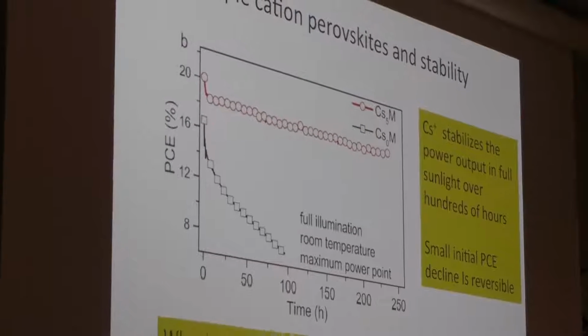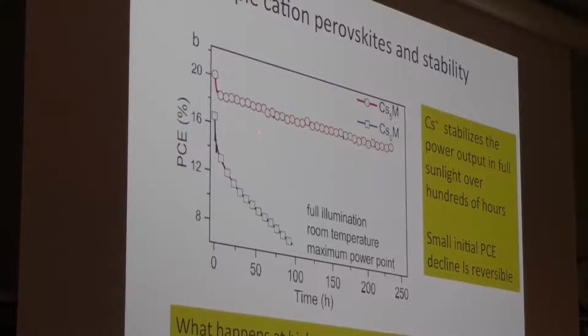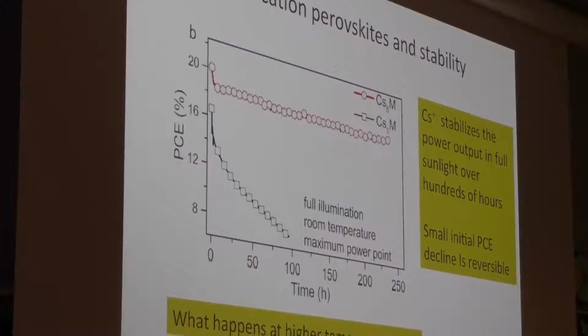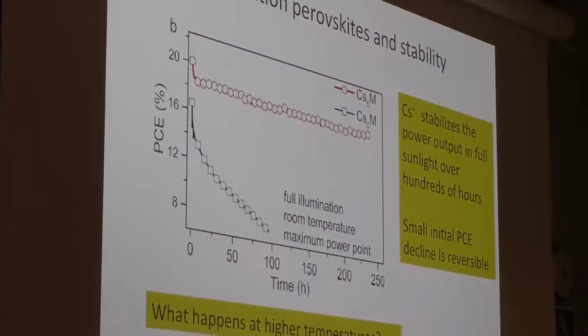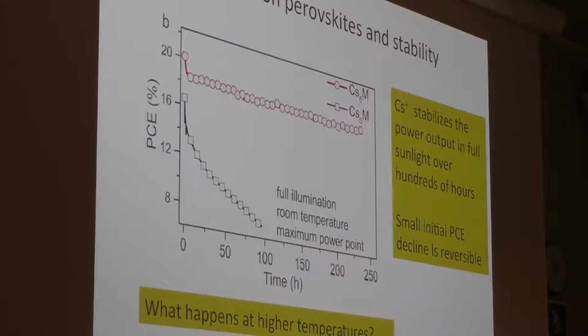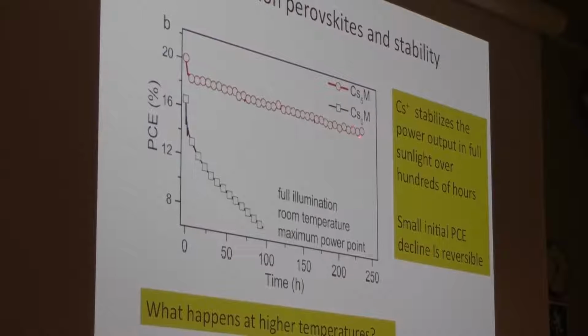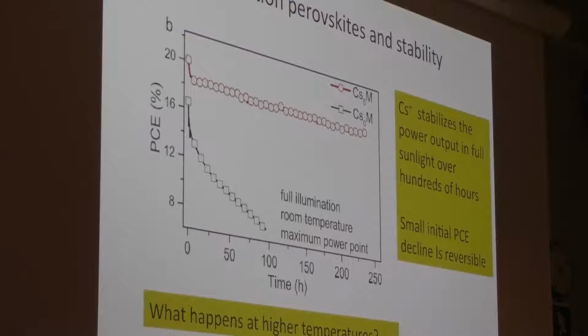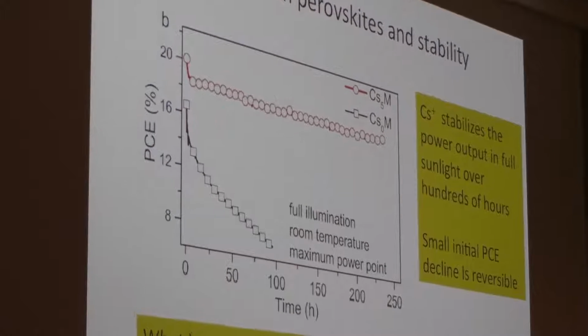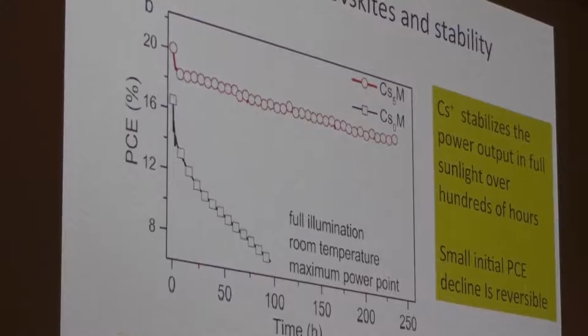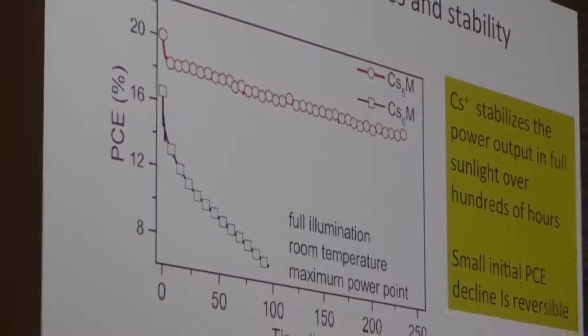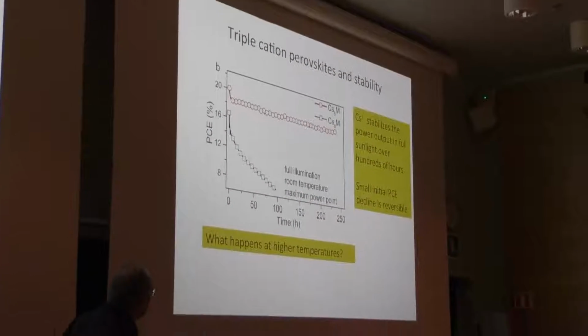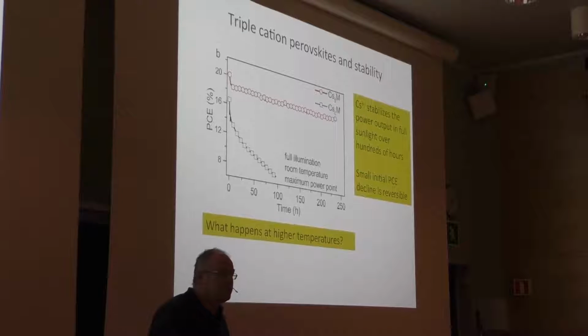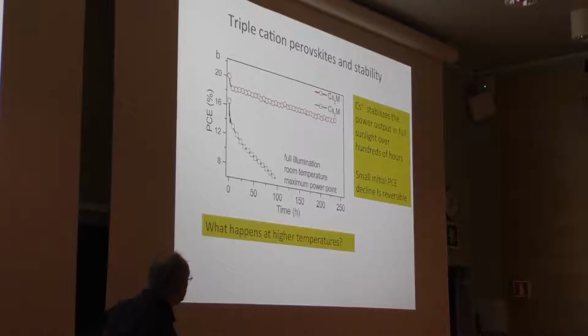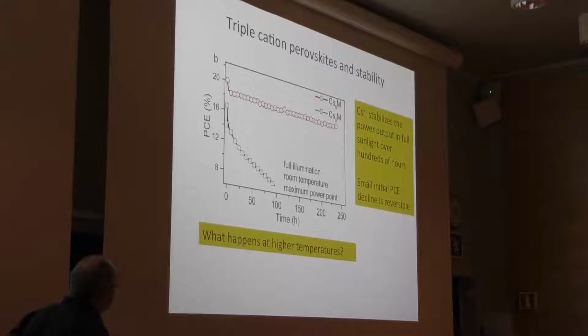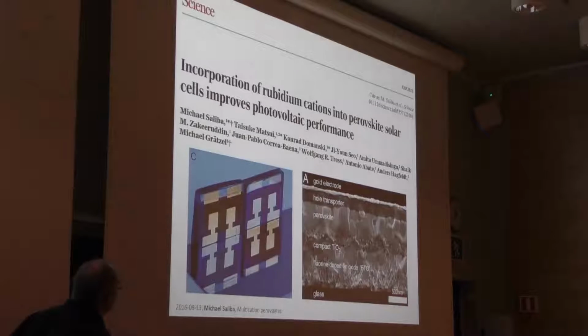So this is a stability test over 250 hours. It's full sunlight and operating all the time, so it's maximum power point, we call it. We start at 20%, you see then it's quite stable for 250 hours with cesium. Without, we have a much faster degradation, let's say. So it improves stability. This is now still room temperature, so I would come back to this question, because what happens at high temperature, that's the next thing. But cesium improves the stability, let's say.